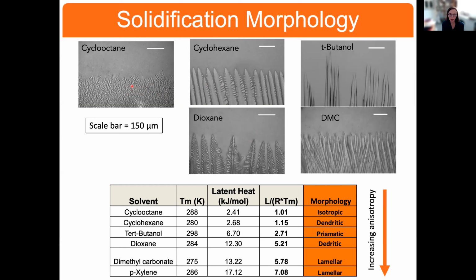solidification takes place along a length here, but then it can nucleate and grow in a different direction, as we see here, much as you see in seaweed. Where here with the cyclohexane and dioxane, we have these dendritic structures, the prismatic structures, and ultimately the lamellar structures in the solid.